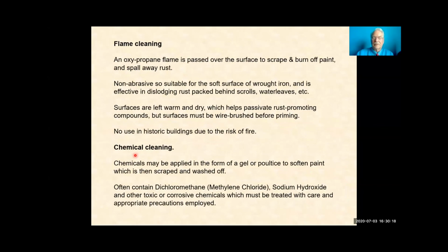What we do like to use is flame cleaning. So you use an oxypropane flame or oxyacetylene, and you pass it over the surface to spall away the rust and to burn off the paint. It's non-abrasive, so it's very good for wrought iron. It's very good at getting rid of rust that's packed into places like behind those little scrolly decorations or the little decorative water leaves. You always get the rust down the back.